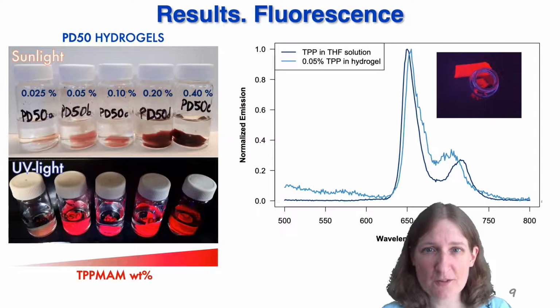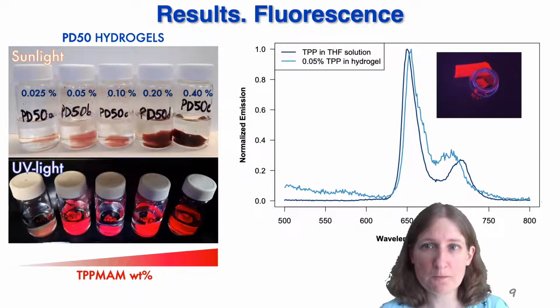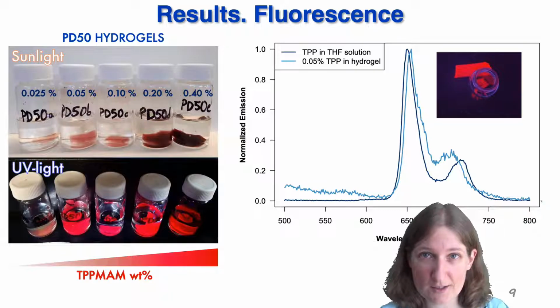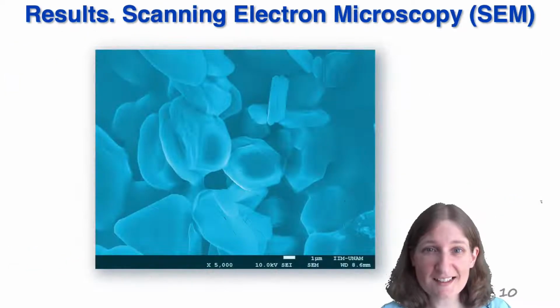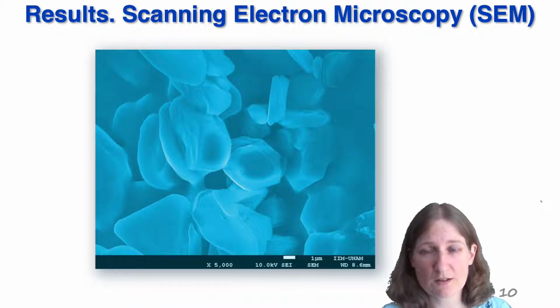The fluorescence emission of TPP-MAM observed in solution was detected in the solid state for all the TPP-MAM-containing fluorescent hydrogels. Scanning electron microscopy revealed a rough surface, a morphological characteristic present for effective water absorption.